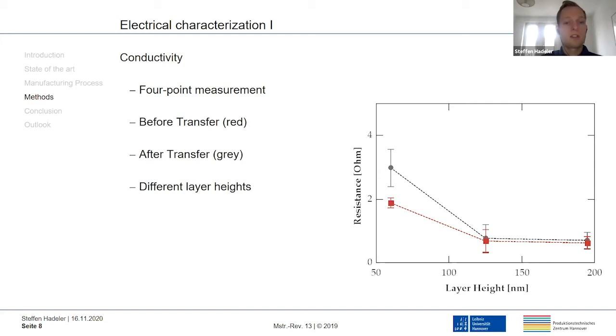In the right figure, the measured resistances before the transfer are shown in red, and the resistances after the transfer to the PDMS are shown in gray. It can be observed that at the lowest tested layer height, a significant increase of the resistance was measured, but from a layer height of about 125 nanometers, a defect-free transfer to the PDMS is possible, and no significant increase of the resistance was measured. Based on all these results, all subsequent investigations were performed with a layer height of 125 nanometers.